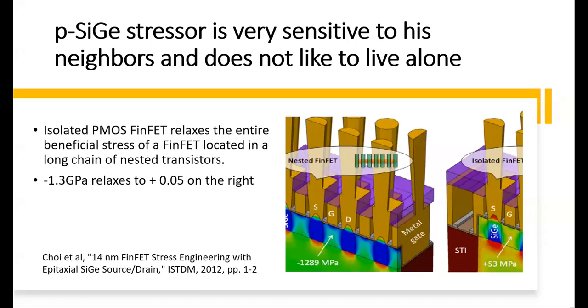But they still have problems. In fact, I still had problems. P stressor is very sensitive to its neighbors and doesn't like to live alone. What I mean is that you could see in this simulation, and it's actually happening in real life as well. The nested FinFET, the strain is uniform. Okay, so the SiGe, and they squeeze this one, you could reach about 1.2 gigapascal. Very nice. And with that, you boost up your current to a good number.